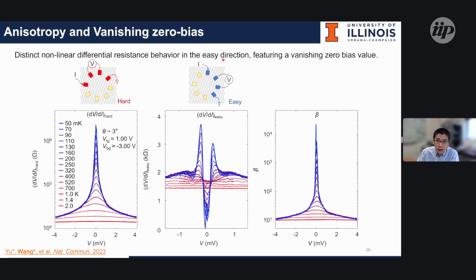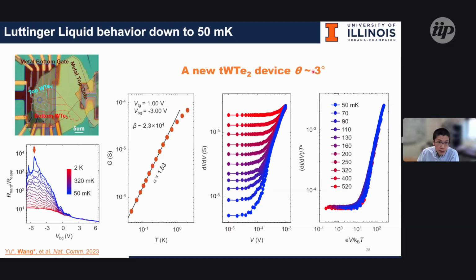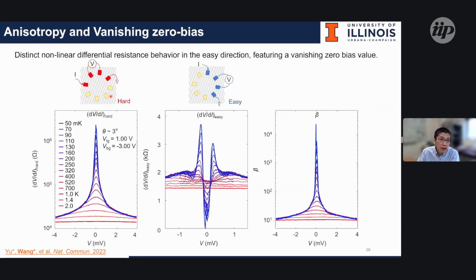This was done in three degree devices. Moreover, if we measure the transport across the wire versus along the wire, the behavior with external bias is completely different. In the high anisotropy region, if we plot the external bias on a linear scale instead of log scale, you can see the differential resistivity drops significantly with external bias.